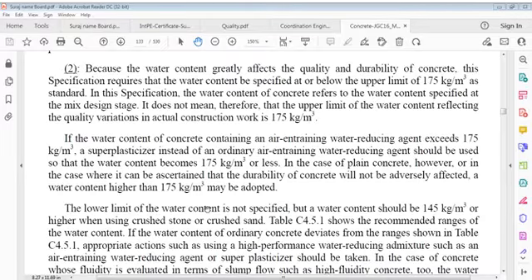In this specification, water content of concrete refers to water content specified at the mix design stage. It doesn't mean, therefore, that the upper limit of water content reflecting quality variation in actual construction work is 175. If water content of concrete containing an air entraining water reducing agent exceeds 175 kg per cubic meter, a superplasticizer instead of an ordinary air entraining water reducing agent should be used so that water content becomes 175 kg per cubic meter or less. In the case of plain concrete, however, where it can be ascertained that durability of concrete will not be adversely affected, water content higher than 175 kg per cubic meter may be allowed.